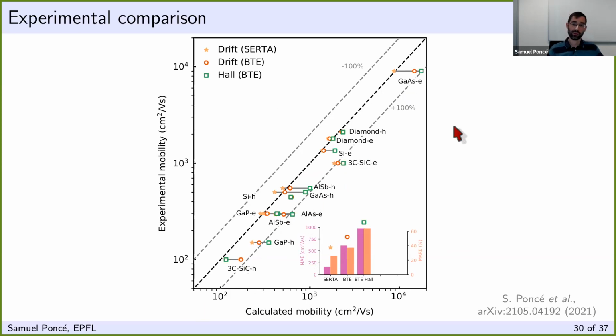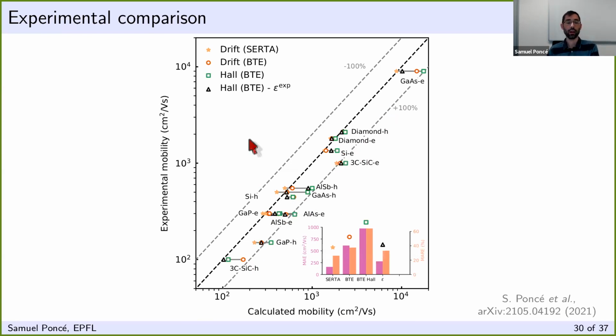In a way, this is expected because we are only considering electron-phonon scattering. So we are not considering other scattering mechanisms that will reduce the mobility. So we do expect to overestimate experiment. However, it's still quite significant compared to experiments. So we can try to understand why we are overestimating so much, by about 100% in some cases.